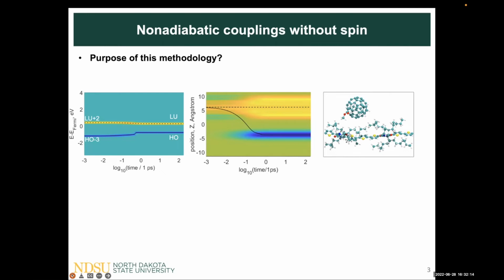But for the project that we are doing right now, we developed a condensed 3D periodic DFT model. So we packed multiple chains and acceptor units, ran force field calculations to reach the experimental density values, a completely packed system. And then we are running non-adiabatic couplings.